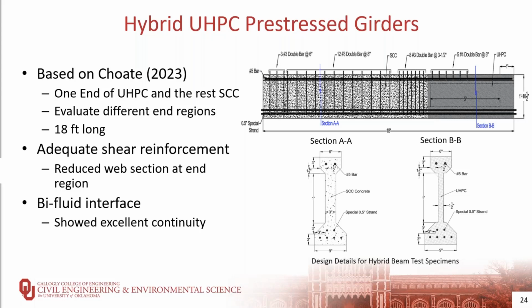All the girders were designed to obtain a shear failure to evaluate shear strength of the girder end regions and to investigate the effectiveness of the composite behavior of the UHPC-SCC hybrid sections. These tests will be conducted after the prestress losses have stopped changing significantly, so we haven't done those tests yet. And in order to obtain the shear failure, we reduced the web section of the UHPC end region, resulting in a different cross section as shown in section BB here in the bottom right figure.